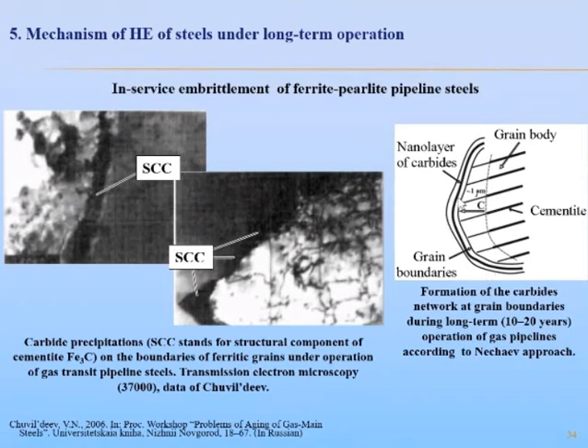And according to his calculations, for formation of the carbide at grain boundaries, it's enough diffusion of carbon from the grain body to the boundaries at a distance of 1 micron only. During, of course, a long term, 10, 20 years of operation of gas pipelines. And this phenomenon is associated with maintenance pipeline steels under operation.